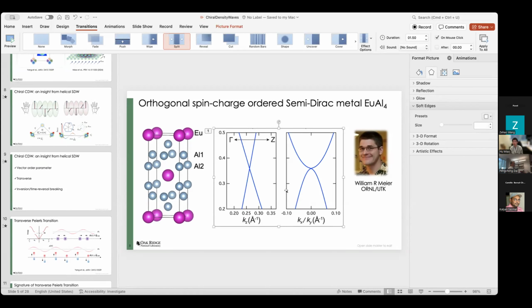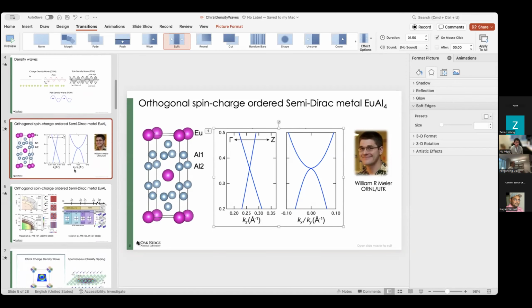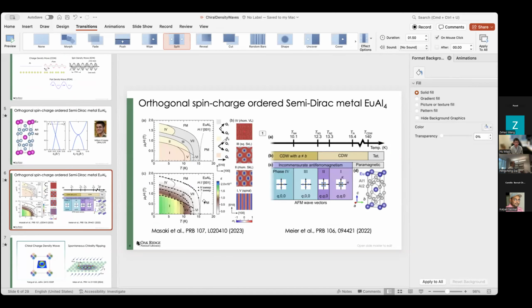I see. That's very interesting. But we need to check a little bit more. This is an ongoing project, and we are interested to see how the doping is going to change the chiral to C2. It would be very interesting to know what your chiral CDW does below the chiral spin order, to see whether there's actually direct coupling or not. Another possibly interesting thing is that at zero field, below 12 Kelvin, the structure is C2. But if you apply a magnetic field of maybe 1 or 2 Tesla, the structure changes from C2 to C4 again. Yes, you see skyrmions.